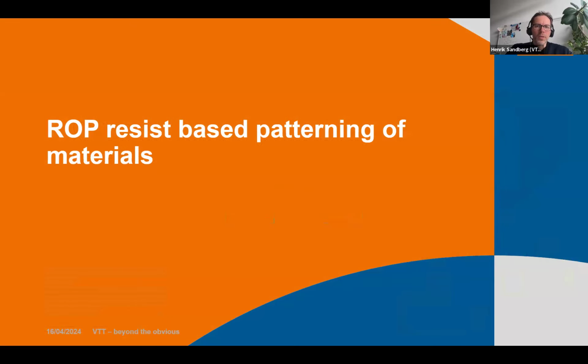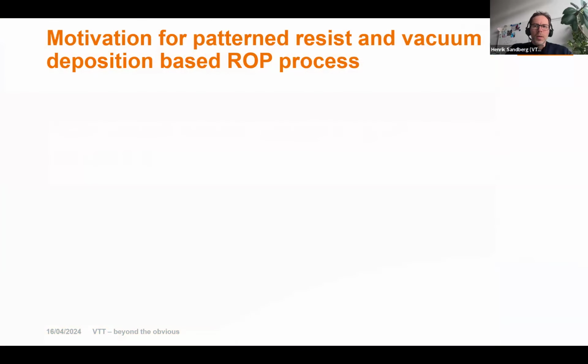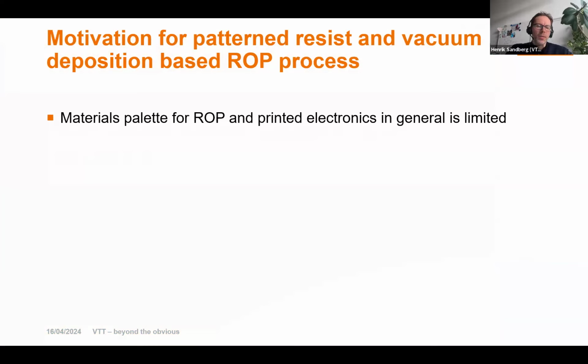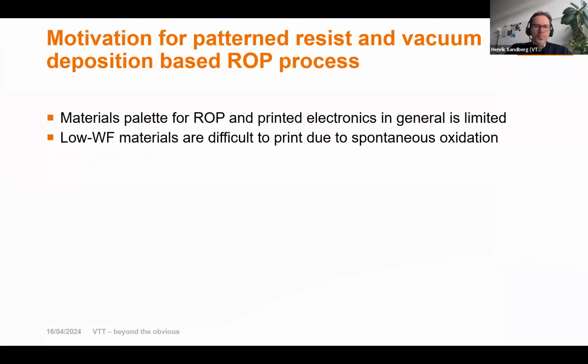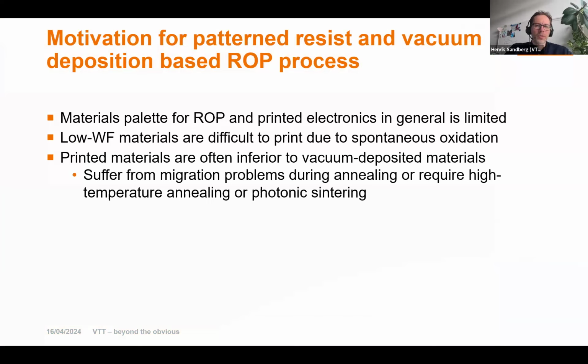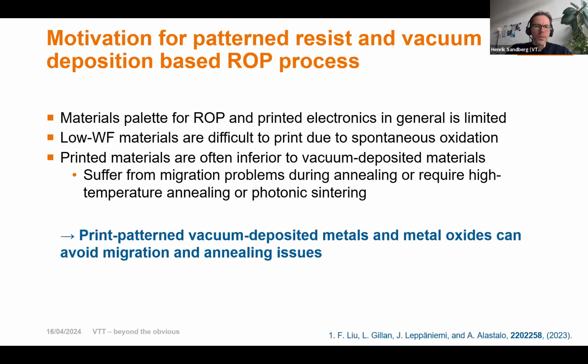So now we see the resist patterning, and the motivation for this really is that there are not so many materials available in ink form which are suitable for this method currently. So to be able to widen this spectrum of material, you can do this resist patterning. You can then apply another layer from solution, or you can do it in a vacuum deposition. And this, of course, widens the range of applications at this stage of the development. The target, of course, being that we would have all the required materials available in ink form so that we can print them directly in an additive process.